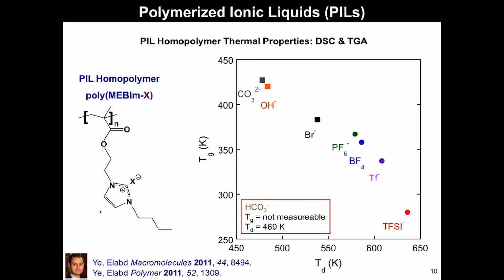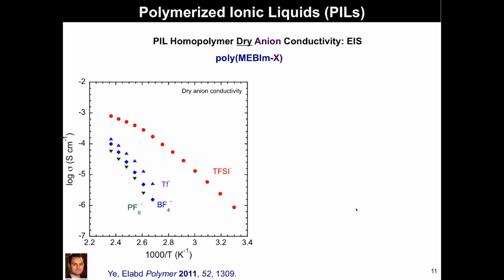If you look at all of these counterions on the same polymer, just the significant difference in the glass transition temperature, where the largest one here at the bottom, TFSI, this fluorinated one, has such weak ion pair interactions that it'll have a Tg that's even 100 degrees below that of just PMMA. That's a non-ion containing polymer. And you could just see this sort of scales with size. As you lower and lower the size and increase the ionic interaction of the ion pair, your glass transition temperature will rise.